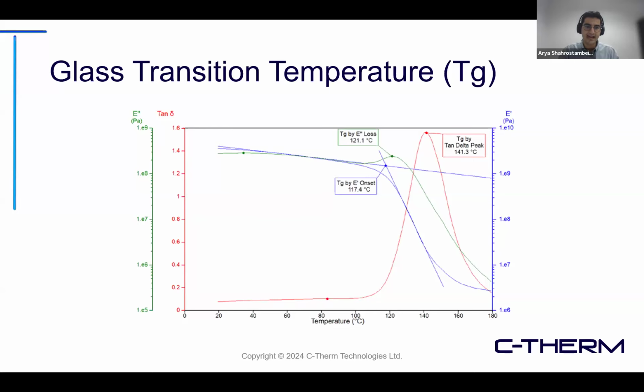As you can see, we have 3 plots here. On the y-axis on the left, you see loss modulus, and you see tan delta in red, and on the right side, you see elastic modulus or storage modulus. We see that on approaching the glass transition temperature, there's a drop in elastic modulus, which is anticipated, and you can obtain glass transition temperature by that drop, or by loss modulus or tan delta. It shows itself as a peak in tan delta. The drop in elastic modulus is called the mechanical approach to find glass transition temperature.